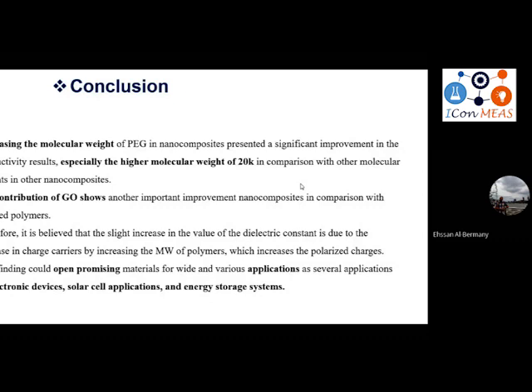So, as a conclusion from this investigation, increasing the molecular weight of PEG in the nanomaterials represented a significant improvement, especially with high molecular weight, which has better properties. This investigation shows us the molecular weight has an impact on the properties of the polymer.